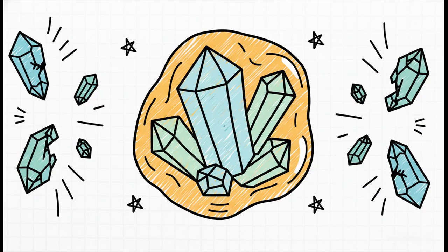But creating those clinoenstatite crystals introduces a whole new problem. When they cool down, they desperately want to shrink and shatter. So to survive this radical transformation, those added fluxes we mentioned way back at the start, like the feldspar, melt into a literal liquid glass. The firing process must generate exactly a 30 to 40% glass phase. This molten glass physically wraps around the newly formed crystals, creating this protective, stabilizing armor. That way, the plate doesn't just self-destruct the second it returns to room temperature.